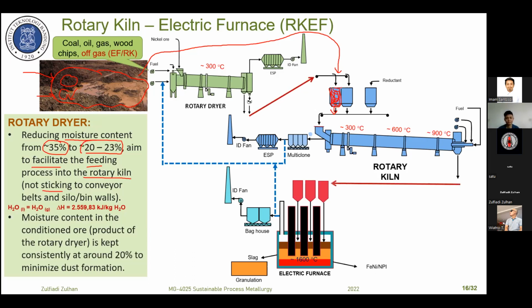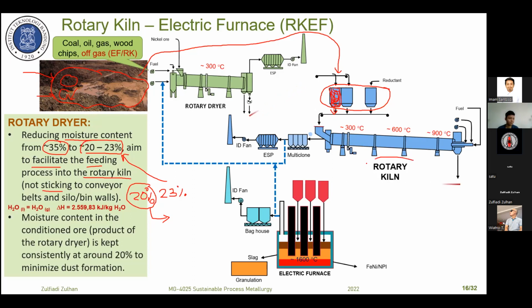In that case, before we send to the rotary kiln, we must remove the water, and this water shall be controlled around 20 to 23%. We must control the ore moisture to a maximum of around 20%, which is the common value for the moisture content in the dry ore from the rotary dryer. The aim is to get stable operation of the rotary kiln and also the stable operation of the electric furnace.